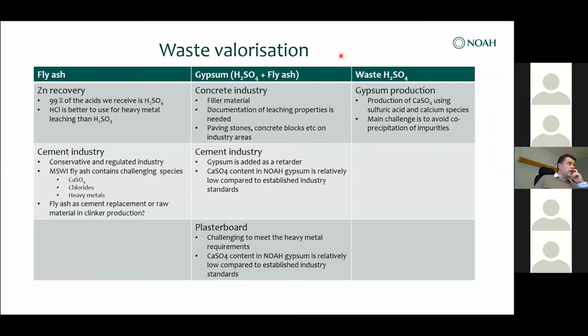Then I have the final slide, where I will talk about waste valorization, which is the topic of this conference. Our main raw materials are obviously fly ash, gypsum, which is a combination of sulfuric acid and fly ash, and our waste sulfuric acid. We have also been looking into zinc recovery because we have a lot of acid. The problem is that 99% of the acid we receive is sulfuric acid, and the solubility of zinc, lead and other heavy metals is very low in sulfuric acid because the sulfate concentration is very high and suppresses the solubility. HCl is obviously a much better acid to leach out heavy metals, but we don't have HCl. So it's not easy to see how we can develop a zinc recovery process based on the waste streams we have now.